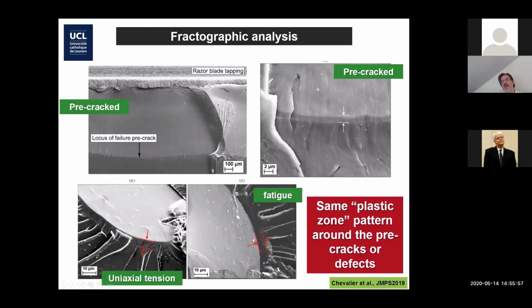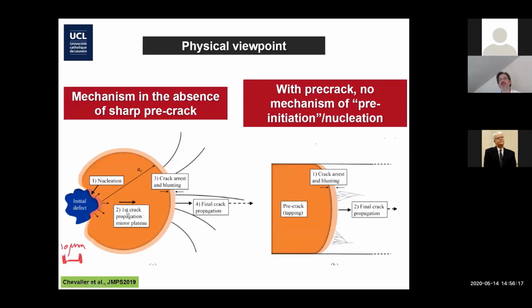It has the size it should have for a plastic zone based on the fracture toughness. You see this zone. If you put a pre-crack, a very sharp pre-crack, we don't see the flat zone. Basically, we only see the plastic zone. It's like if the pre-crack is sharp enough to play the role of this flat zone. So the message we got from analysis of the fracture surfaces is the following.